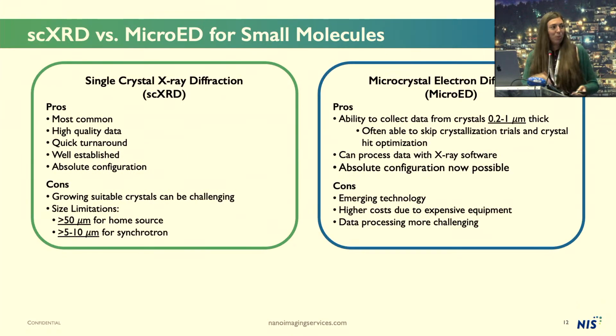Which moves me to a comparison of these two orthogonal techniques. Single crystal X-ray diffraction is by far the most commonly used technique to solve crystal structures. It produces really high quality data, has very quick turnaround times. It's just a very well-established field with decades of work and instrumentation. With modern collection techniques, you can generally get absolute configuration information, and it's just a great overall technique. The only downside really is growing large enough crystals to perform your single crystal X-ray experiments. For some compounds, this can be quite challenging, and some crystal forms may never be able to form a crystal large enough for X-ray.